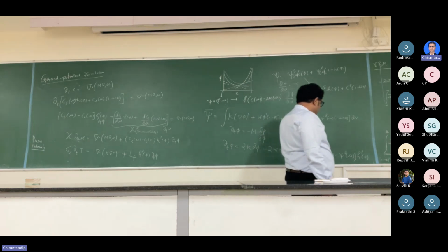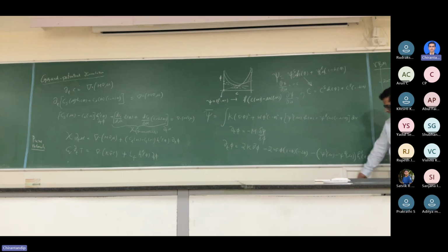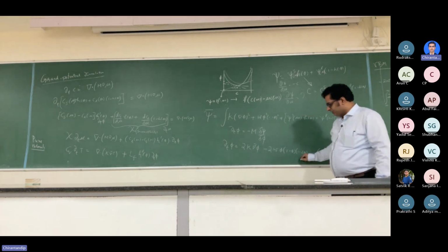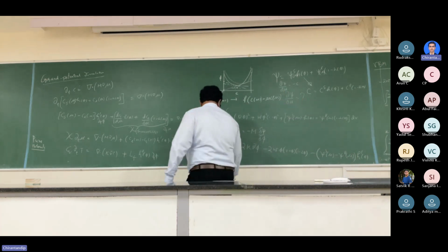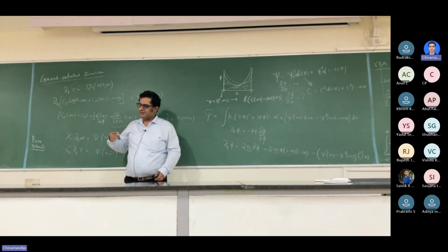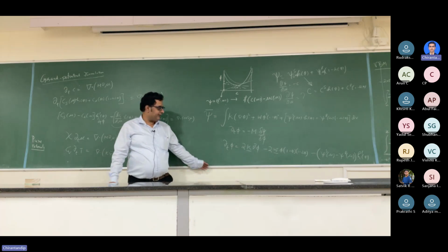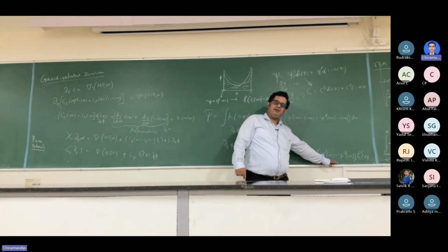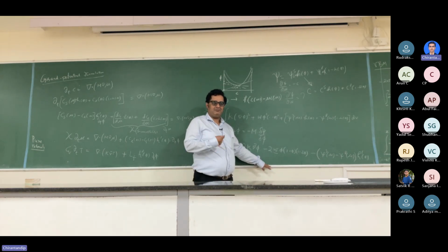And because of the structure, I don't need to rederive anything, because at equilibrium, all of you have agreed that at that mu, these 2 will become equal because they will intersect. So the resultant equation will be the contribution of only these 2 terms, and dT phi equal to 0. So the structure of the equation on the phase field interface will be directly a function of A and W, as it was in the original chemical model, as it was in the case of the pure materials, as it was in the case of the KKS. Right? So you have complete independence of the alloy thermodynamics, which is here, and the interfacial properties that you want to add. It's just the mechanism by which you go.